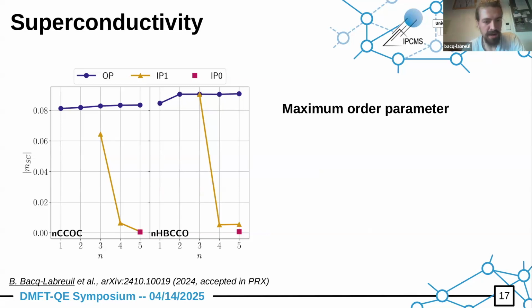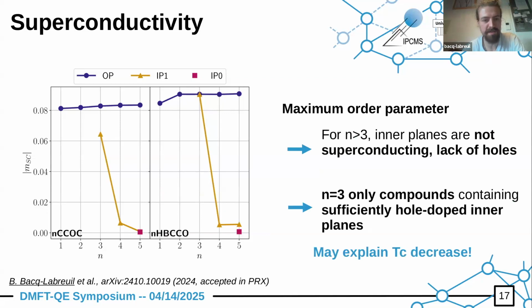What is striking here is that for the n=4 and n=5 compounds, you can see that the inner planes are not superconducting. They are not superconducting because they lack holes, basically. The n=3 compounds, those are tri-layer compounds, are probably the ones which provide the best compromise between having inner planes which are protected from any kind of disorder that would come from doping, but still doped enough such that they can really host superconductivity. And this may explain why this critical temperature has a maximum at n=3.